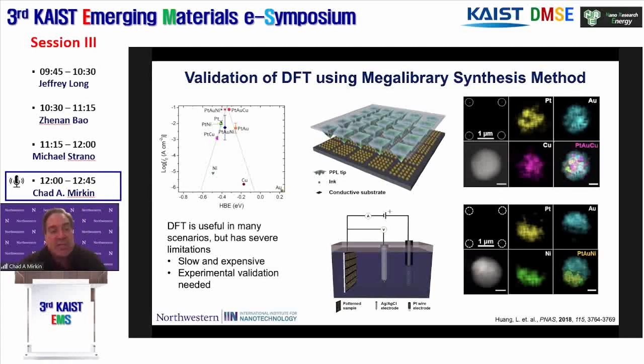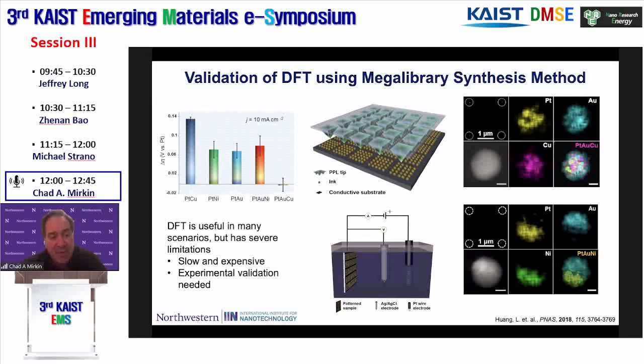And in a volcano plot, you'd like to have materials at the top of the plot. And what you can see is platinum's not at the tippy top. In fact, these three component systems which we've made, platinum, gold, nickel, and platinum, gold, copper, are at the top. Well, we can then go and use polymer pen lithography and make arrays of these on a glassy carbon electrode, and then begin to probe their properties. First, their structural on the right, and then their catalytic properties on the left. And what you see over here on the left is if we compare these to platinum and ask how do these compare to platinum in terms of overpotential, it's really quite remarkable.